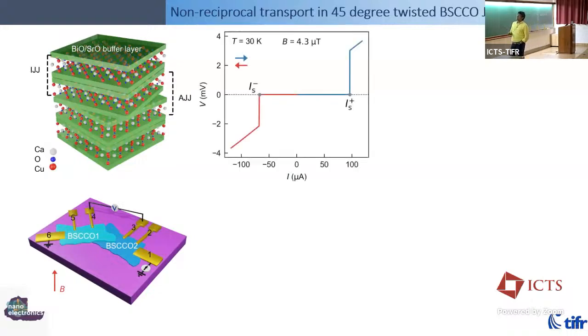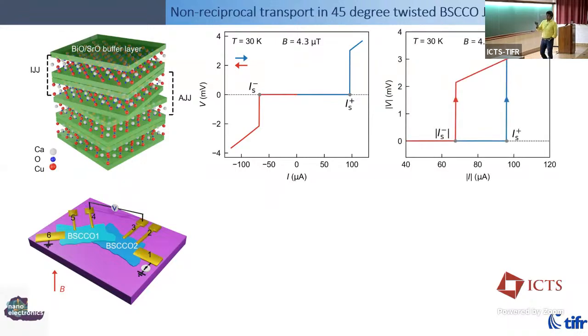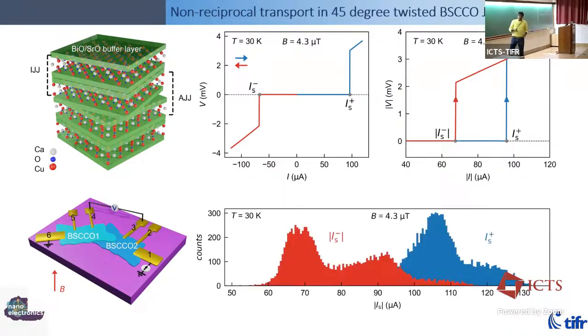So we make these kinds of devices and we started measuring the response of this device. And what we see is that the switching current of these two sides is different. Okay, and this is at 30 Kelvin. You'll also see a magnetic field being applied to it, and I'll talk about it later. So these are Josephson junctions because what's happening is that you have one superconductor and a kind of twisted superconductor, and there's one order parameter, and the order parameter of the lower one is rotated by whatever is the angle of twist.